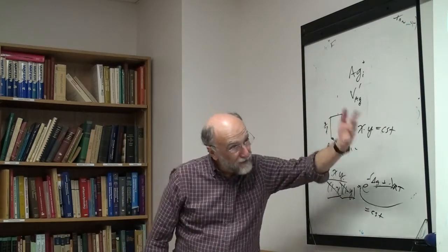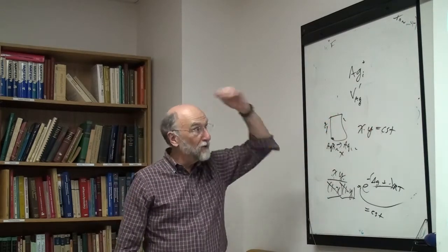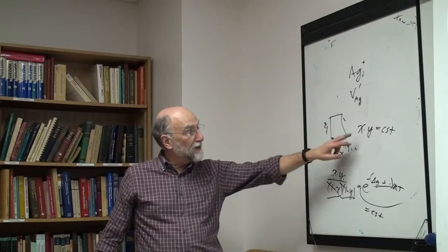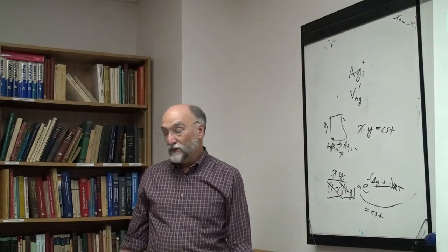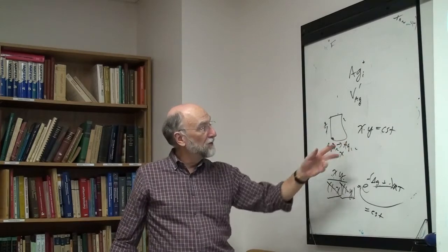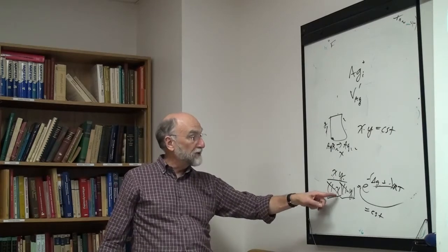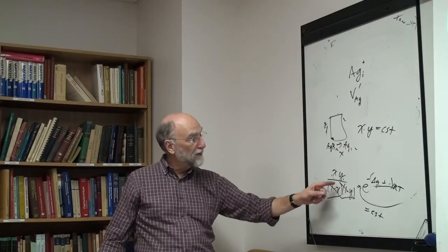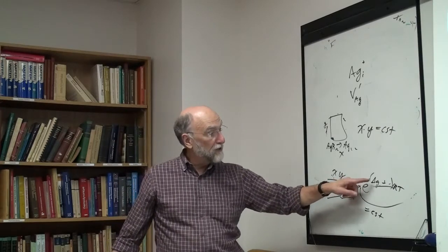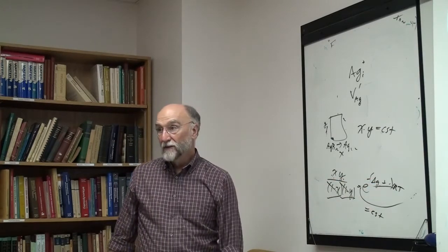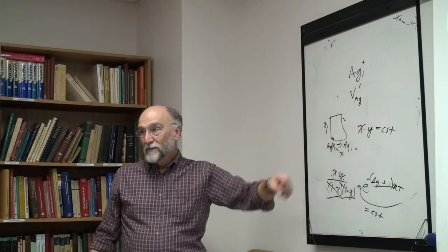If you want to do it more exactly, these are the main terms in the equation. You have other terms, but they're secondary. Basically, as the concentration of one point defect goes up, the other point defect concentration goes down. They're dilute solutions, so from xy over approximately 1, x and y are small, so the denominator is 1. X times y is a constant, which is the exponential of the formation energy of the defects over RT. This isn't exactly true, but it's close to being true.